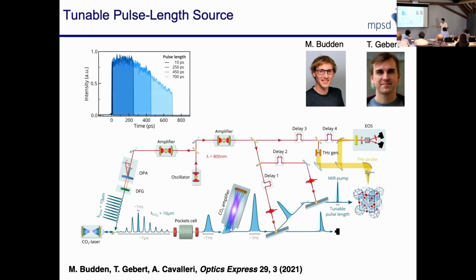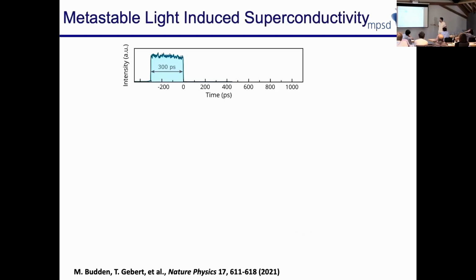These are technical things, maybe more than this audience is interested in. This is now an experiment in which I am pumping with a square pulse which is 1,000 times longer than the 300 femtosecond pulses I had before, but with basically the same area as the one I was using before, with a factor of 2 higher. And remember, before I was pumping here with 300 femtoseconds, and this thing was going beep, beep, and coming back in a picosecond. Now I'm pumping for 300 times longer.